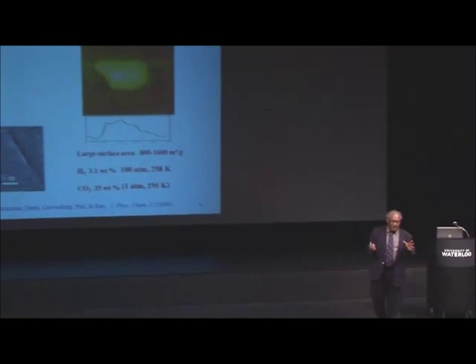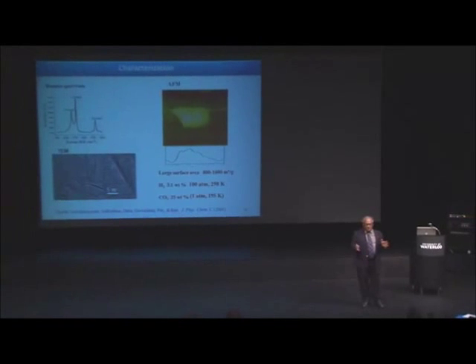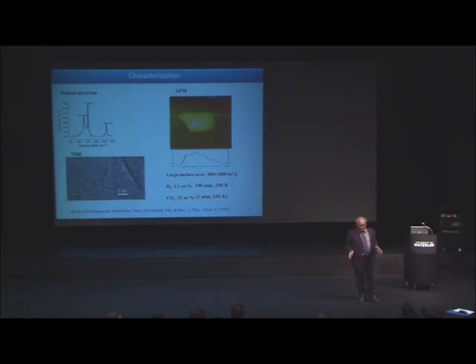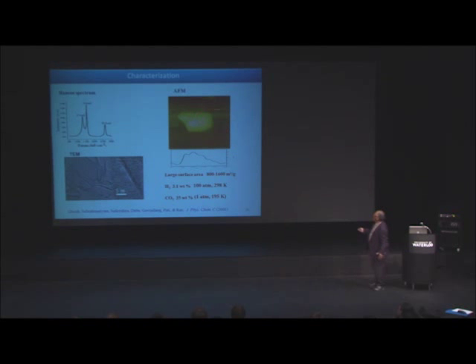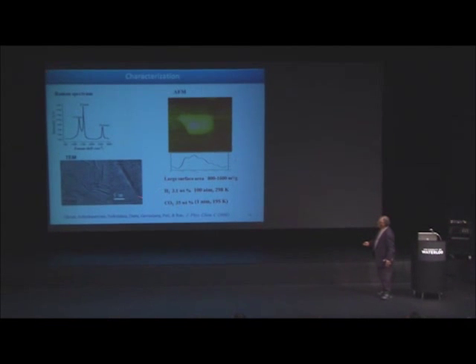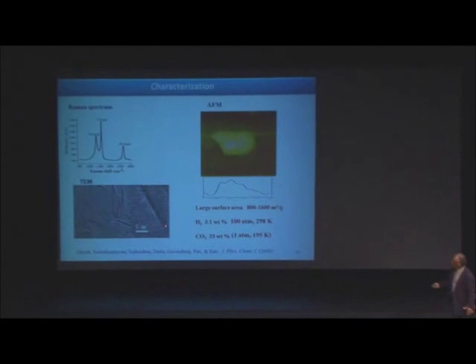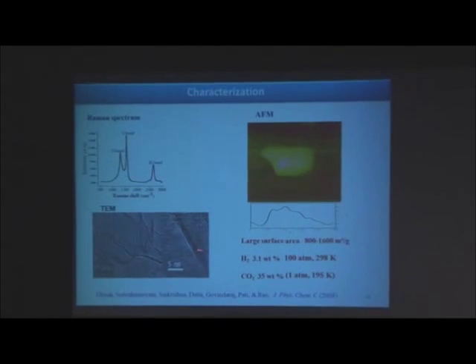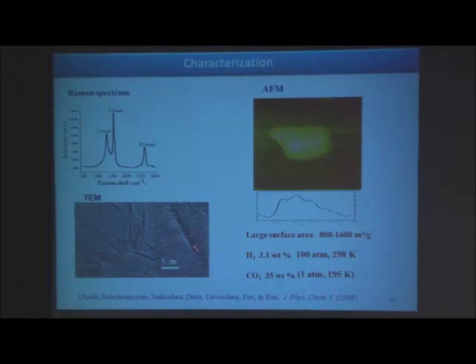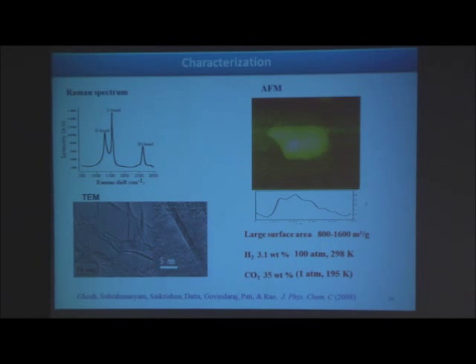As I told you, whatever you get, it is just a summary slide. You first do Raman spectrum. Don't forget, any paper that I get in this area without Raman spectrum and atomic force microscopy, I don't accept it because you must do those to characterize graphene, okay? So you do atomic force microscopy, measure the height, and if possible, transmission electron microscopy. You see here is something we made with 4 layers. You can see the 4 lines there. So you can measure by TEM.